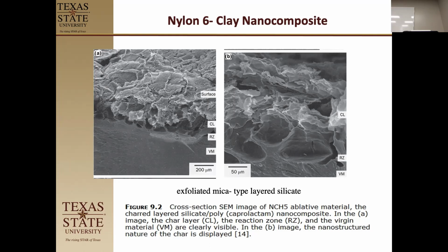Why is the reaction zone necessary? Well, the stuff on top has already reacted with all of the heat. This is the heat that's soaking through to the virgin material. When you started, the entire thing was virgin material. The first layer gets heat, and then that forms a char layer, and you're still soaking heat in. So you're not having direct contact with the gases, but you have a thermal decomposition of the material. Your reactive zone, or pyrolysis zone, is where there is enough heat flux to start decomposing, but it hasn't completely decomposed to non-permeable material, which is the char layer. So it's in the process of becoming a char layer. Does that make sense?